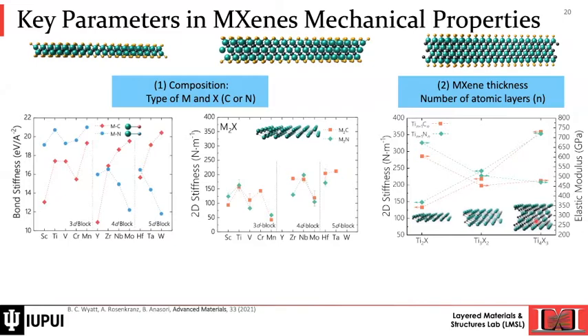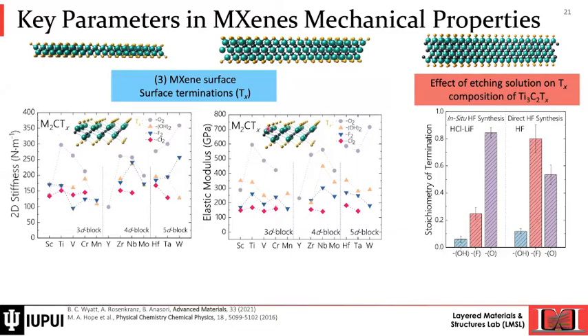Next step is MXene surface termination, the Tx, or the yellow atoms that we have in these slide series. You can see that depending on what surface termination, whether it is oxygen or hydroxyl group or fluorine or chlorine, the 2D stiffness and the resulting elastic modulus vary. Obviously, oxygen will have one of the highest stiffness because of the nature of the bond that oxygen forms with the transition metals. So depending on what surface termination, we can tune the elastic modulus.